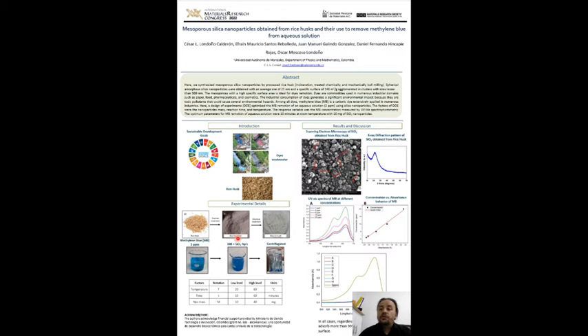The temperature was increased until it reached 700 degrees Celsius and it was kept isothermal for 1 hour to increase the amount of silica by reducing the carbonaceous materials. The ash obtained was subjected to a chemical leaching process that allows the chemical reaction between the acid and metallic impurities. Then, these reacting metals are leached from the acid solution by washing with distilled water and filtration.